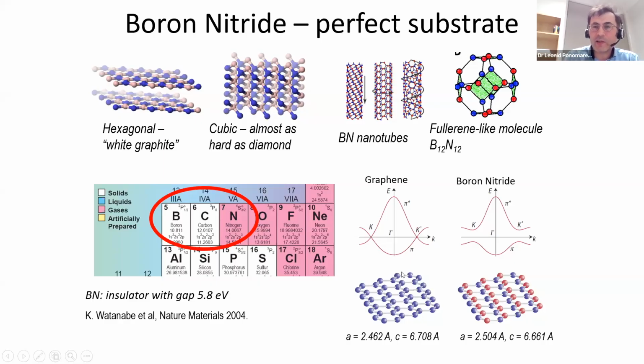And the reason for that is that graphene has inversion symmetry. If we take a sheet of graphene and turn it 180 degrees, it will transform into itself. We cannot do that with boron nitride. For that reason, graphene is a very good conductor, and boron nitride is one of the best insulators. It has a huge gap between conduction and valence band, of the order of 6 electron volts. This is really a lot. So boron nitride, therefore, is an ideal substrate.